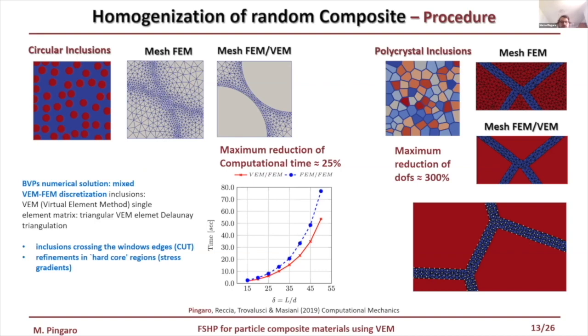In the case of circular inclusions, the mesh is fine near the inclusions and coarse elsewhere, to reduce the time consumption. The time consumption in the case of particle inclusions is reported here. The graph shows the analysis time in seconds as the window dimension varies. The blue line is the time consumption of the standard FEM of degree 1, and the red line is the time consumption of the VEM of degree k=1 adopted in this strategy.